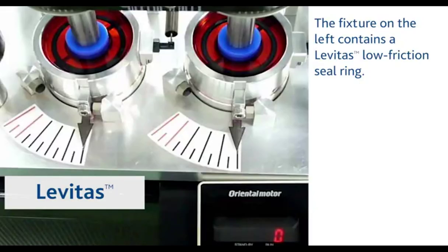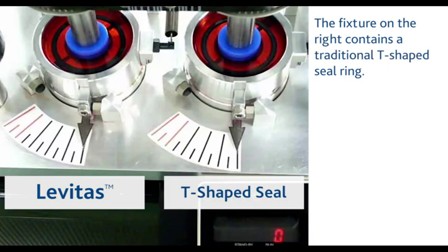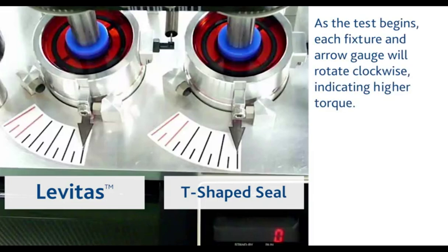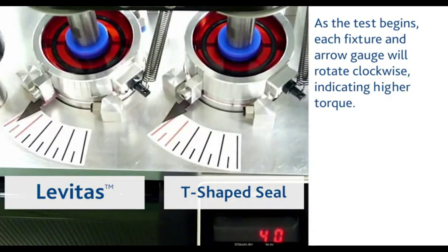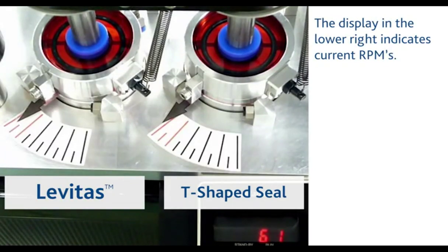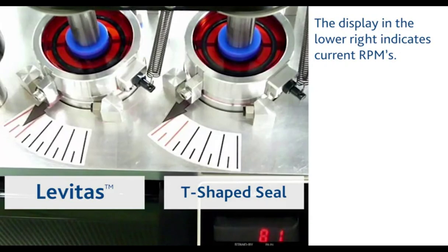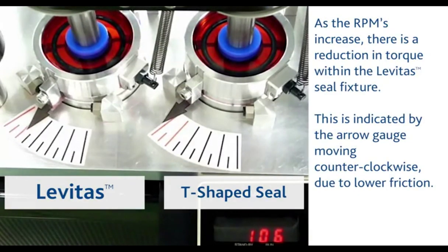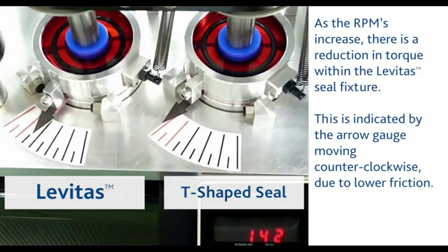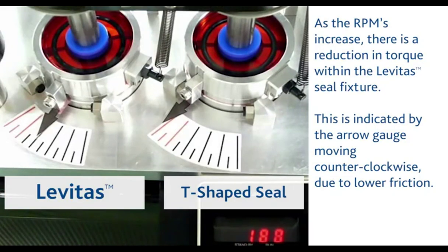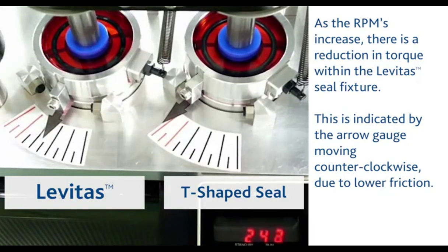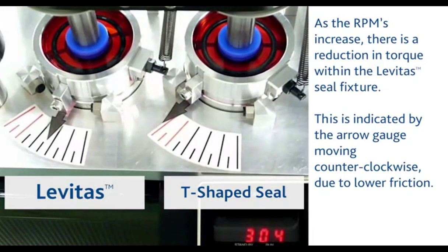The fixture on the left contains a Levitas low-friction seal ring. The fixture on the right contains a traditional T-shaped seal ring. As the test begins, each fixture and arrow gauge will rotate clockwise, indicating higher torque. The display in the lower right indicates current RPM. As the RPMs increase, there is a reduction in torque within the Levitas seal fixture. This is indicated by the arrow gauge moving counterclockwise due to lower friction.